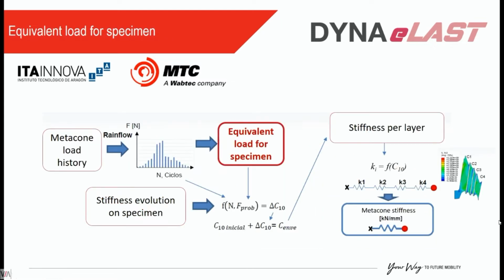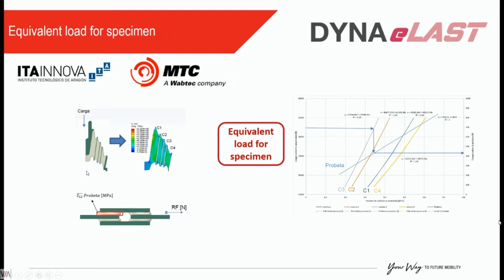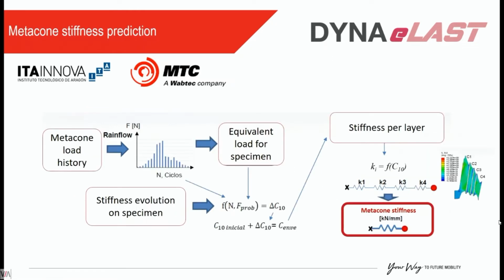To determine the equivalence for the specimen, we take into account the stresses on each of the layers of our element, and we replicate those in our specimen, and that's how we have our equivalence. We have our diagrams to be able to apply the correct loading to the specimen. And finally, like I said, once we can predict the evolution of C10, we can, through finite elements or whatever, have the stiffness for each of the layers. We can combine them to get the metacone stiffness.